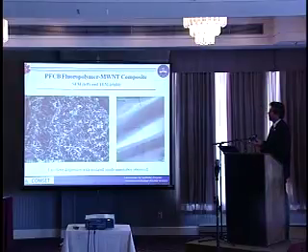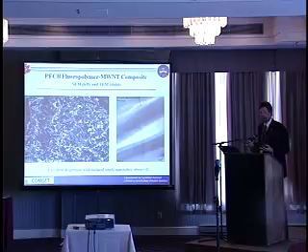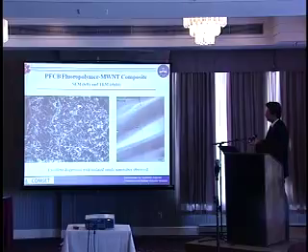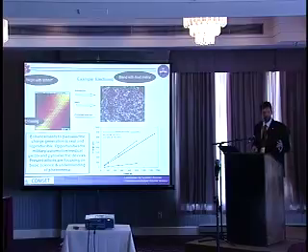We've also found, this is a patented technology, dispersing nanomaterials in fluoropolymers or halogenated polymers in general. That's a very, very efficient way to disperse nanoparticles. This just shows an example of excellent dispersion and even single-wall carbon nanotubes found in this fluoropolymer. And with that, some very nice technology is coming out of Tetramer Technologies and Clemson on using carbon nanotubes, very, very low levels, 0.05%